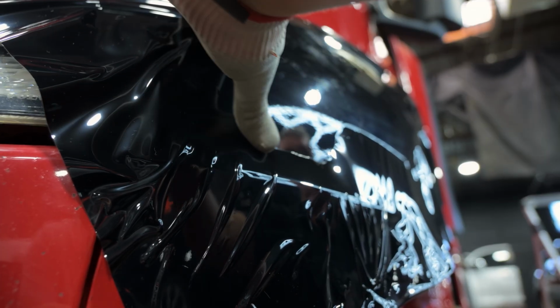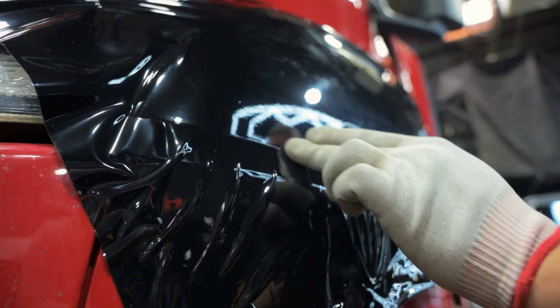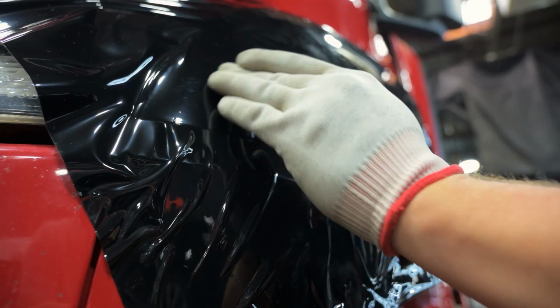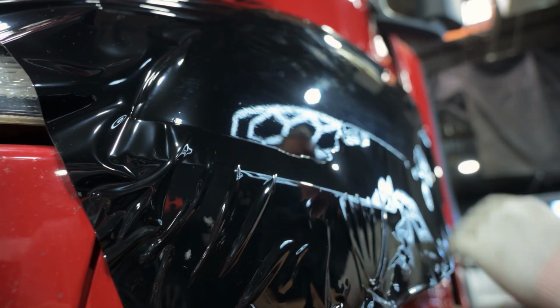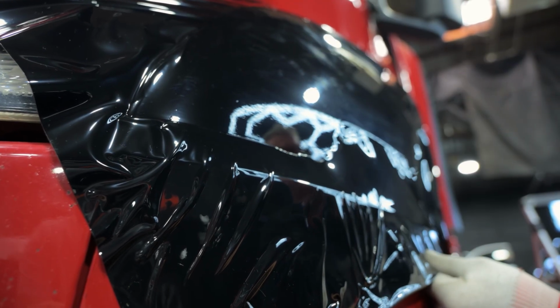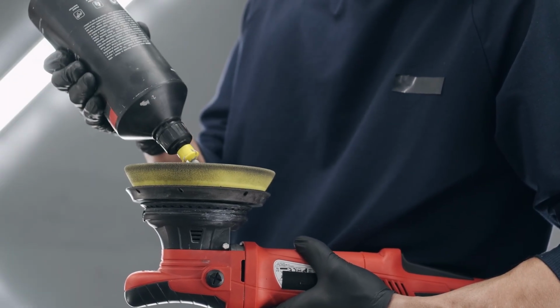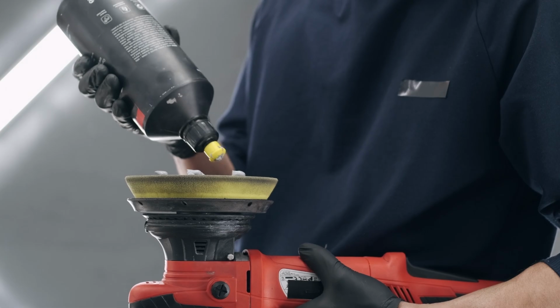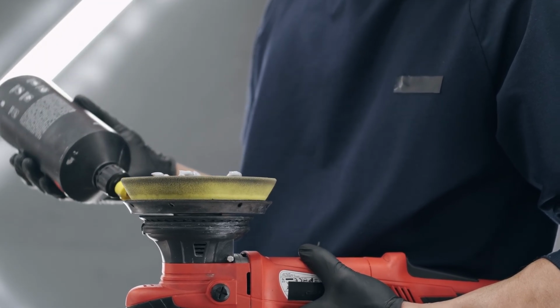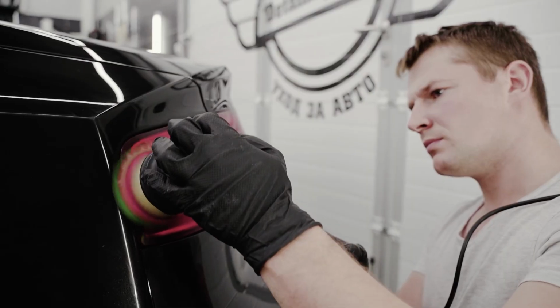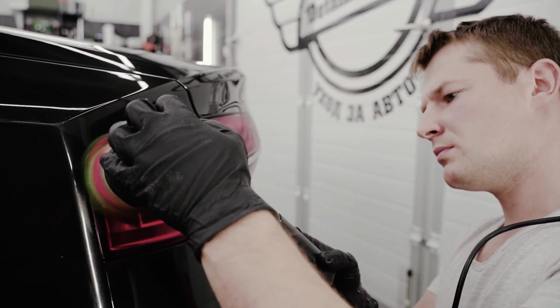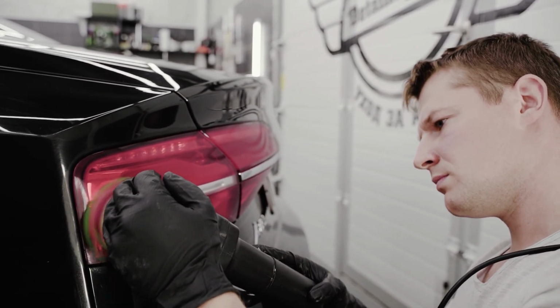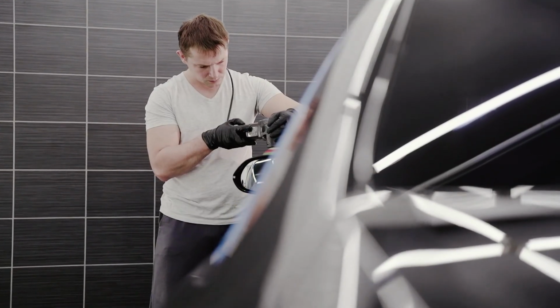Number 7. Polishing technique with aluminum oxide compounds. For those that prefer the traditional mechanical finish, the number 7 is the polishing technique with aluminum oxide. Unlike the supermarket polishes, the German professional compounds utilize decreasing microabrasives. These aluminum oxide grains break during the polishing process. They start large to eliminate sanding scratches, and they finish being nanometric particles that give the mirror finish.